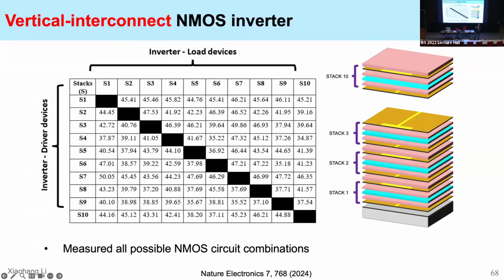So you can actually reduce the amount of power consumed for a transistor to talk to another transistor. So in here, we can, for example, interconnect the transistors from stack 5 to stack 4, stack 6 to stack 2, basically a matrix. We can do any interconnect as we want. And then we demonstrate that these inverters have pretty good gain, around 40 to 50, right? Which is actually comparable to the state of the art.